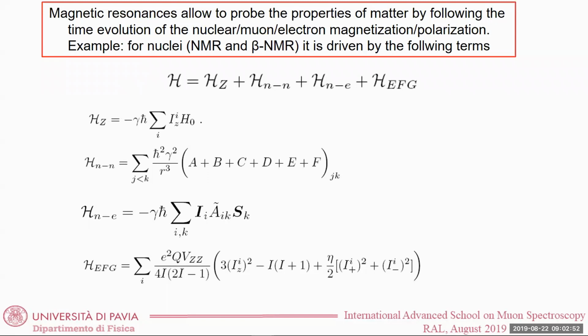If we take, for example, just to start with NMR, the nuclei, which are present both in nuclear magnetic resonance and the beta NMR technique. In general, the nuclei are sensitive to the Zeeman Hamiltonian, namely the interaction with an external magnetic field, if we apply one. We are sensitive to the nuclear dipolar Hamiltonian, the interaction between nuclear magnetic moment dipoles. We have the hyperfine interaction between the nuclear magnetic moments and the electron magnetic moments, this nucleus-electron hyperfine interaction. And there is also, for those nuclei which have a spin larger than 1/2, the electric quadrupolar Hamiltonian.